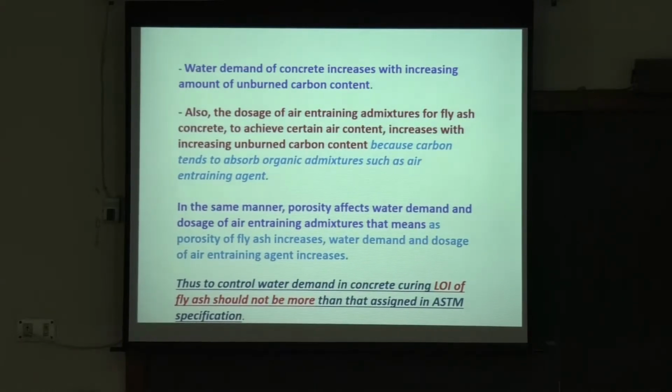In the same manner, porosity affects water demand. As porosity of fly ash increases, that means if you have more cenosphere, please make a note, water demand and dosage of air entraining agent increase. Thus, to control water demand in concrete, the LOI of fly ash should not be more than a certain limit assigned in the standards. Because if you have more carbon, then all these things will happen.